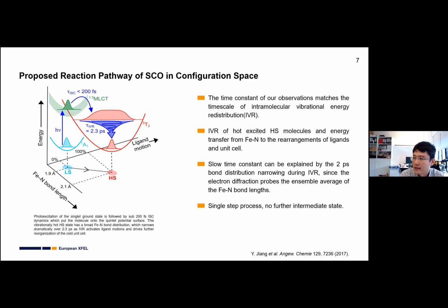Also, it's important to notice the time constant we obtained matches with the time scale of intramolecular vibrational energy redistribution obtained by transient absorption. And this IVR of hot excited high-spin molecules involves energy transfer from iron-nitrogen to the rearrangement of the ligand and the unit cell. The slow time constant can be explained by the 2 picosecond bond distribution narrowing during the IVR, because our electron diffraction is probing the ensemble average of iron-nitrogen bond lengths. So for this part, I will further compare it with the next work. So in the end, we see a 1-step process and no further intermediate state.